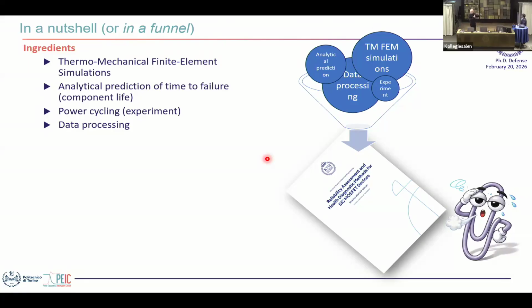You did this simulation of double-sided cooling with different spacers. I was trying to find the conclusion: which ratio of copper and molybdenum would you recommend? Can you answer this? There are 3 solder layers and we get different viscoplastic dissipation density in those 3 layers. From the paper, it looks like the die-attach solder layer will fail first, and molybdenum is the worst because there it's highest.